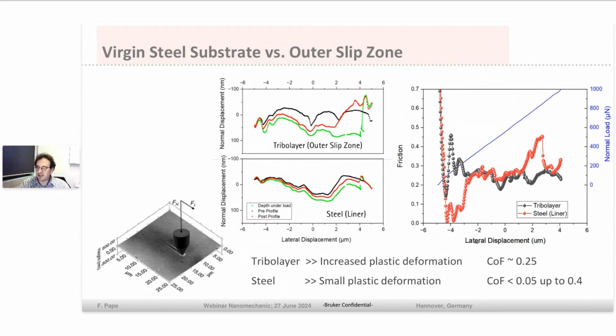When we go to the upper diagram, we have here the black curve. It's a scan under very low load of 2 micronewton along the surface to achieve the profile before scratching. After that, we go back to the start on the left, increase the load and perform a scratch test. That's the green curve. And after that, we scan along the surface again and achieve the red line, which shows us the plastic deformation which remains on the surface. Like in this image below, that's the remaining scratch, which is shown here in red. And we can see that the tribofilm formed on the bearing surface features more plastic properties compared to the steel itself, in the diagram shown for the steel liner.